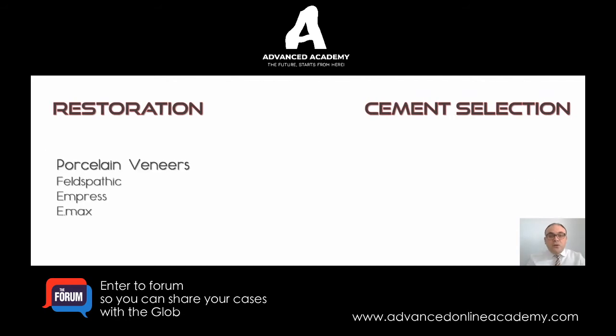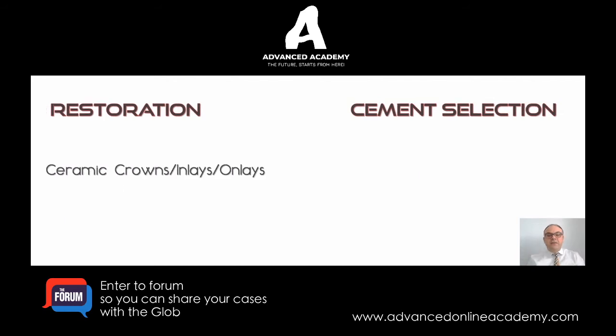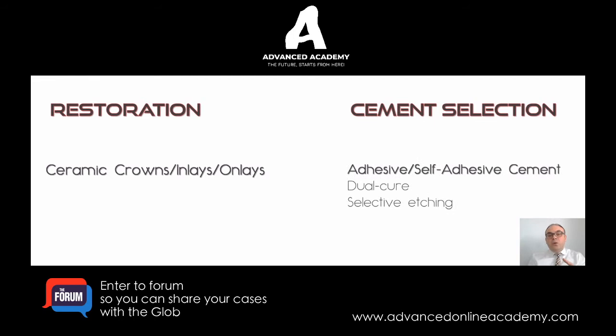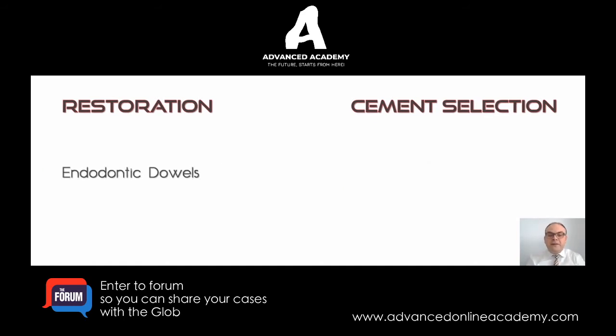For porcelain veneers, whether it's feldspathic or otherwise, I'm going to use a light cure resin cement always, no dual cure. For ceramic crowns, inlays and onlays, if they have minimal retention, we're going to use an adhesive cement. And if they have a little bit better resistance retention form, we're going to use a self-adhesive cement. These can be dual curing. And also, don't forget etching your enamel. It's going to bond the cement a lot better.